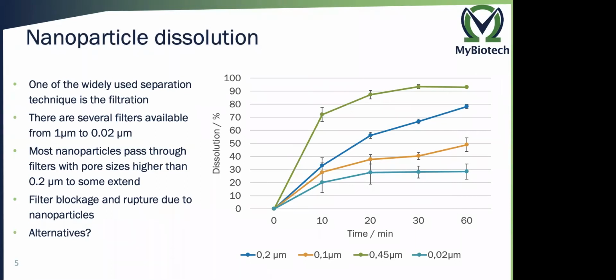We have the 0.1 micrometer filter, where you see a decrease in the nanoparticle dissolution, but especially in this case, I want you to look at the 60-minute value, which is going unexplainably high. That is basically a sign that you have a filter rupture and the nanoparticles start passing through the filter. And if I go down to 0.02 micrometer, it was almost not possible to filter the complete sample due to the blockage of the filter, which is observed by the high relative standard deviation. But here I can understand that the solubility of the nanoparticles in this dissolution medium compared to the dose is around 30%. And depending on the filter type that I'm using for my dissolution studies, I can find anything between 100% to 30%.